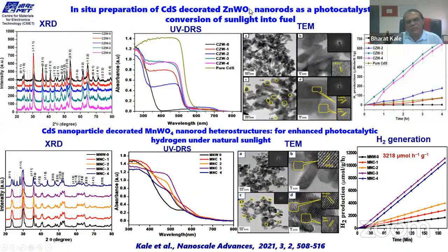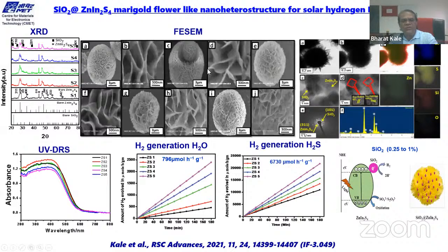Then the same thing we did with ZnWO4. During the in situ work, we produced ZnWO4, and we decorated ZnWO4 with CdS. So cadmium sulfide is decorated on the ZnWO4, and that also worked well. ZnWO4 nanorods are coated with tiny nanoparticles of CdS, around 10 to 15 nanometers, decorated on the nanorod, which helped a lot in enhancing hydrogen production. So this kind of flower-like structure is better, like a marigold structure.